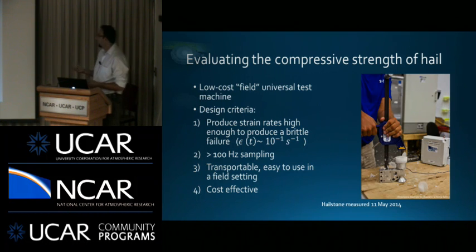And you also have to resolve that peak, so you need fast sampling. I put on there greater than 100 hertz. It really comes down to about 1 kilohertz or so. It's got to be transportable, easy to use in the field, and as I mentioned, cost effective.